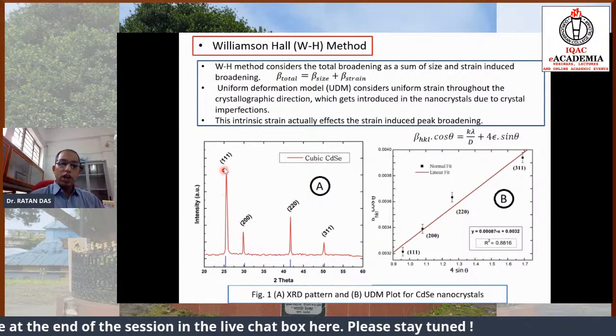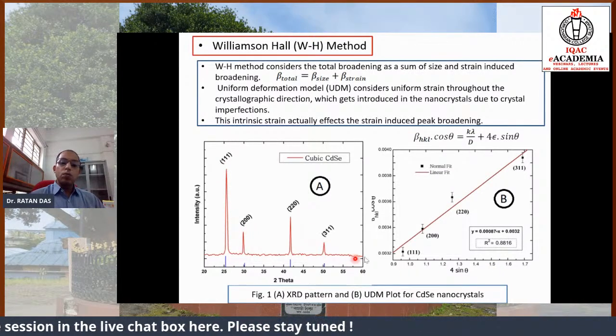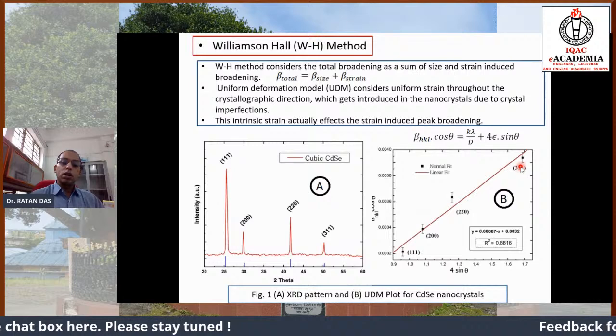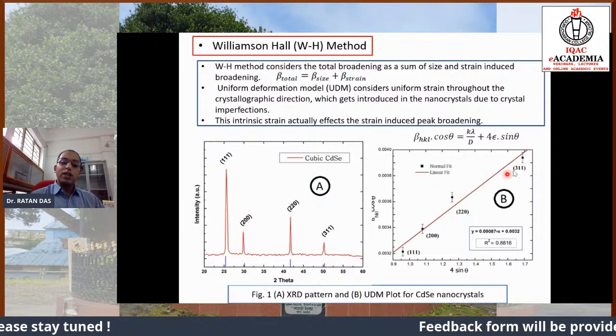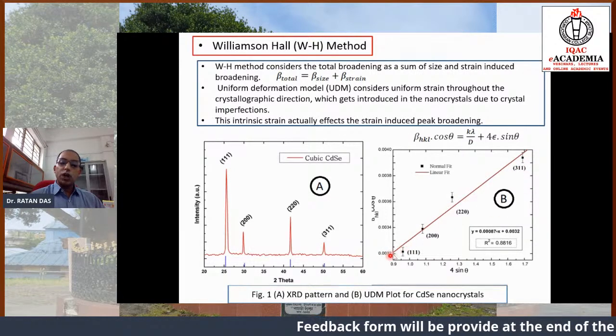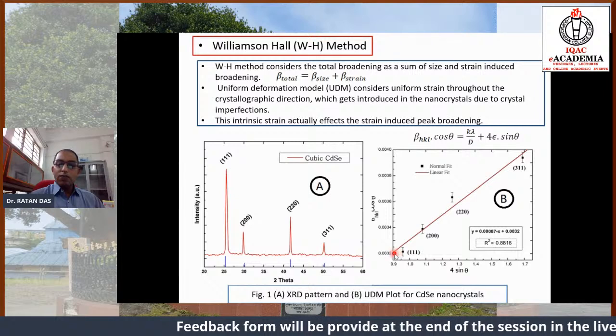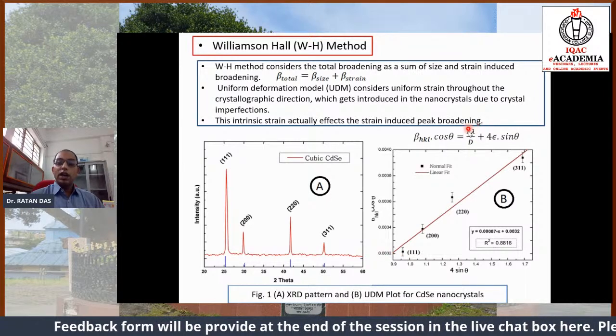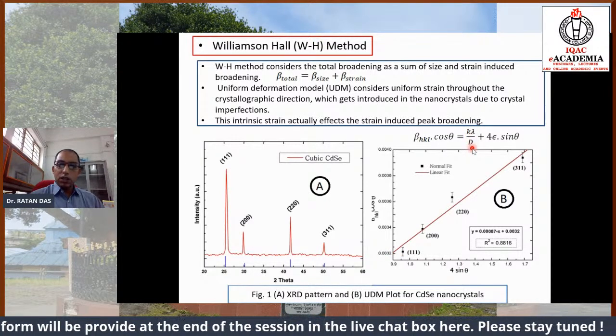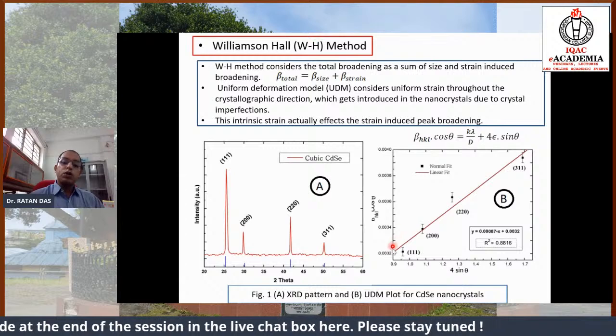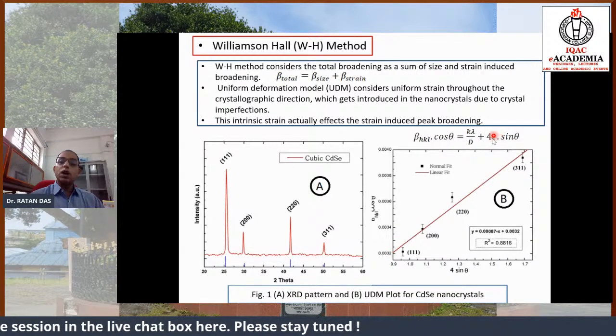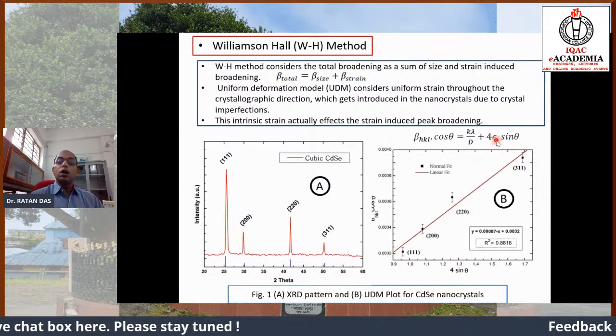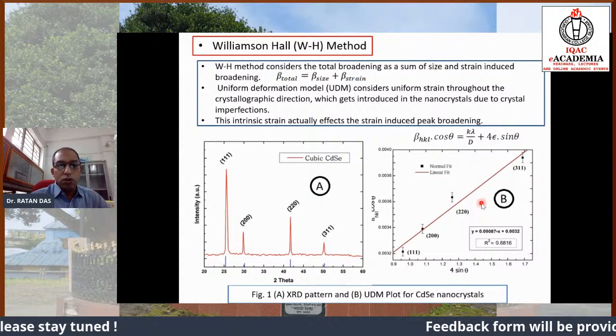Okay, and for every plane we put the values. Then we obtain a straight line. The intercept of the straight line is nothing but K lambda by D. From the intercept we obtain the size, and from the slope we obtain the strain value. This is very simple actually.